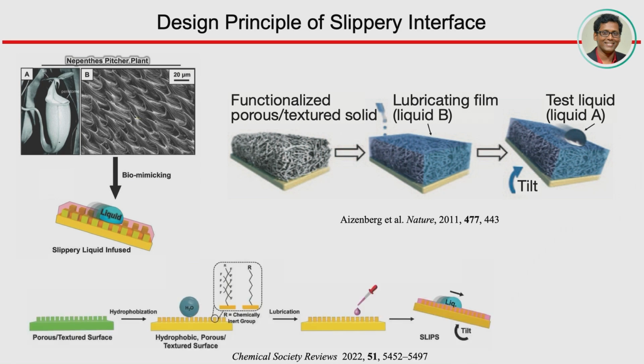Since then, people wanted to explore this field. In general, you come up with a porous and textured surface, go for complete hydrophobization, so it's highly hydrophobic or superhydrophobic. Then you go for lubrication with silicone oil, Krytox, or any type of oil you can think of, and you infuse it. Depending on the compatibility of the surface as well as the probe liquids, you see this sliding behavior. The problem is this lubricant is a liquid in nature, so when you put the probe liquid, it will be contaminated, and over time it will leach out, so it will have a shelf life issue.